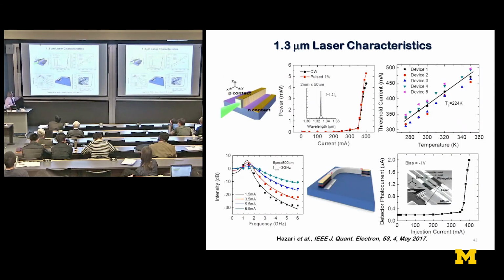So we made lasers out of these, and lo and behold, these lasers actually lase at exactly 1.3 microns. And they show very good temperature stability again. And so one of my students here, Arnab, he actually then made a photonic integrated circuit of a laser, a passive dielectric waveguide, and a detector, a waveguide detector. And here you see that photonic integrated circuit made with the same nanowires. This is something that may be used in silicon photonics, where the active source, the passive waveguide or modulator or whatever, and a detector, they're all there on a 001 silicon platform.